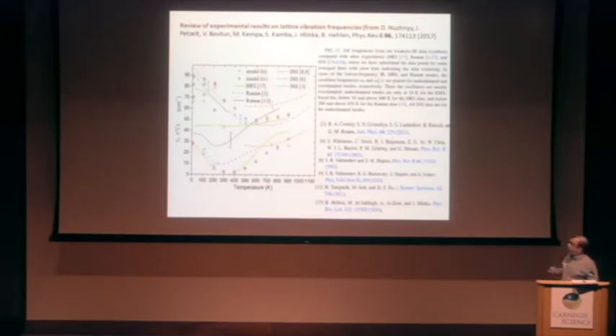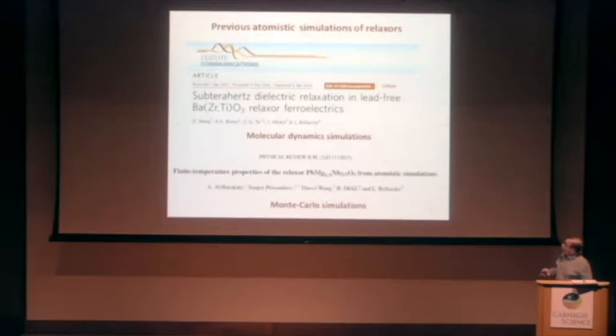Thus, the situation is interesting. Usually, experiment is used to verify the theory. Here we can use the theory to verify experiment and to choose which experimental data fit better the real situation. Our work is based on these two ones. Recently, we published first principle-based molecular dynamics simulations in lead-free relaxor, BZT, but the behavior there is known to be very different as compared to classical PMN relaxor.